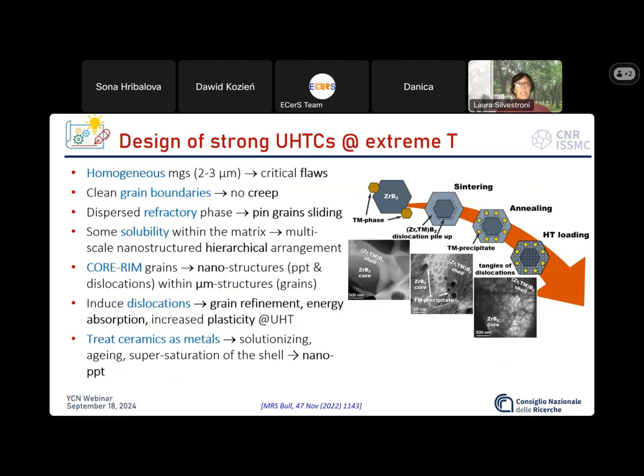So, the key factors for super strong ceramics in the ultra high temperature regimes are microstructure heterogeneities spanning length scales from the micro, second phase, grain cores, to the nano, which include solid solutions in the shell, dislocations, and precipitates. These features interact during the formation, and might have the potential to achieve superior properties and temper the strength ductility paradox in the ultra high temperature regimes.